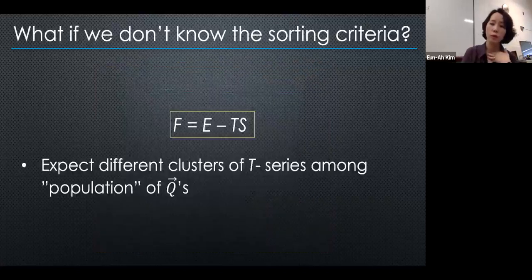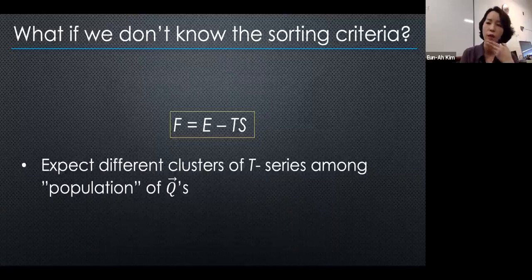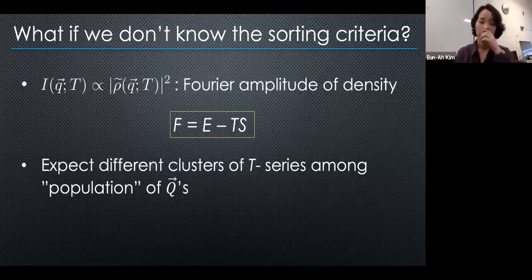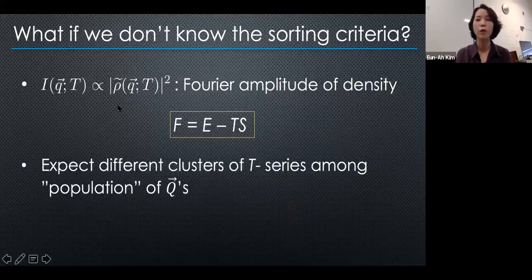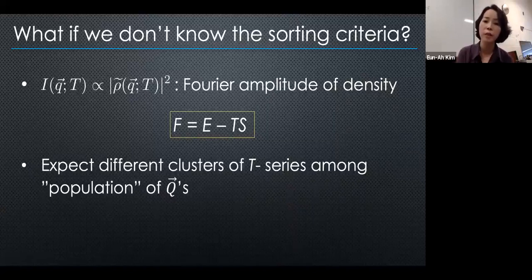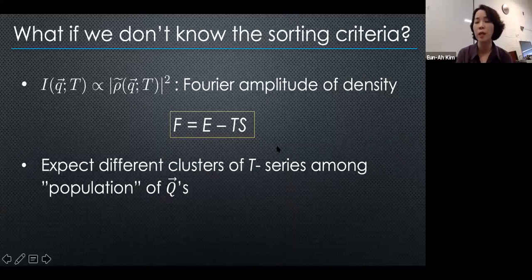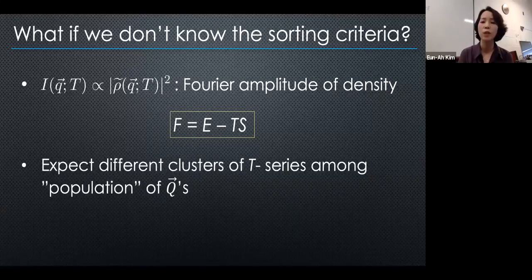What if you don't have obvious sorting criteria? Even if you don't have an obvious sorting criteria just because you don't know what to look for, you can still remember that what you're measuring is Fourier amplitude of density. So as you change the temperature, you're looking at temperature dependence of this Fourier amplitude. And we can always remember something very fundamental when we want to think about ordering phenomena. That is, ordering is dictated by Helmholtz free energy, that there is E minus TS, and it's about the competition between E and S that's guided by temperature. So even if you don't know what to look for, we can expect the different clusters of temperature series among the whole population of Qs can be exhibiting different qualitative behavior, even if we don't know what they are.